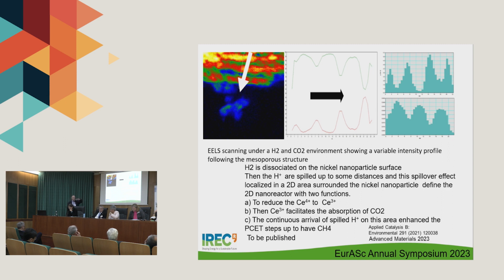The nickel is producing a spillover of the hydrogen, and this hydrogen is reducing the ceria Ce4+ to Ce3+. Immediately, CO2 is absorbed and fixed there, and can receive more and more hydrogen until it is transformed from CO2 to methane. It's possible to determine that the concentration of the Ce3+ is decreasing as you go away from the nickel particle position.